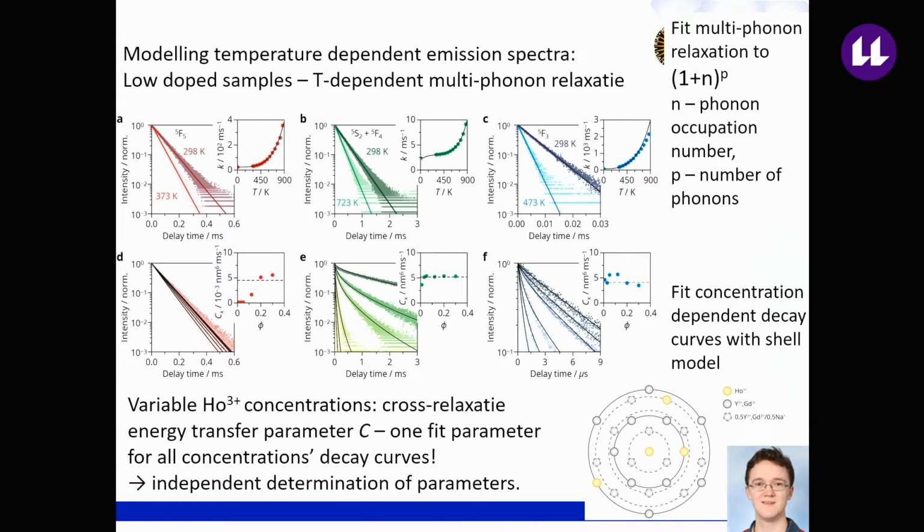Often those ratios between energy transfer, you just measure it and that's your calibration curve. We also wanted to really understand it. So for the low doped host, we measured the luminescence lifetime as a function of temperature for the red, the green and the blue level.